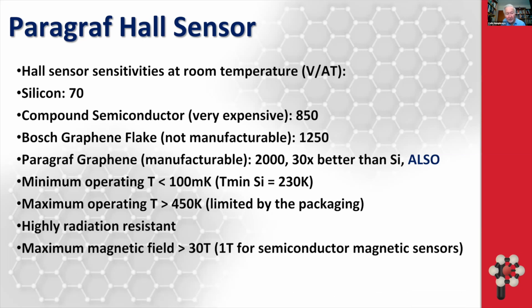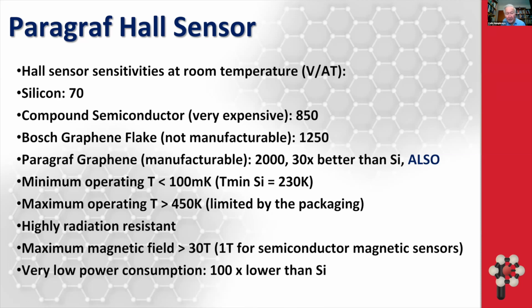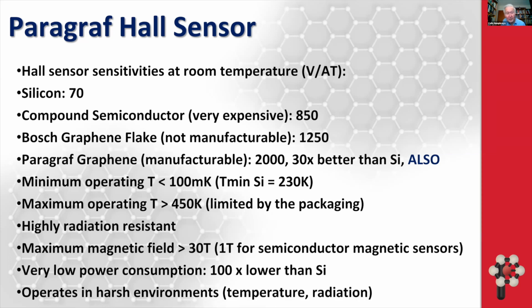It's highly radiation resistant. We can operate in magnetic fields up to 30 Tesla, and the maximum for a silicon Hall sensor or gallium arsenide one is 1 or 2 Tesla. Very low power consumption. I put it 100 times lower than silicon. We now know our radiation result is 1,000 times better than silicon. Really important if we can reproduce that in a transistor because of the energy savings. And we operate in a harsh environment.